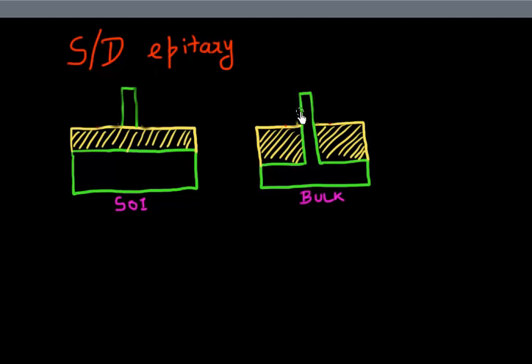And then I grow my source drain from this silicon below. And I grow it in a fashion like this. So I grow my source drain after I do an etch back. And I can do this process flow over here because I have my silicon channel available here. So I can regrow my source drain using my silicon or my bulk as a template.